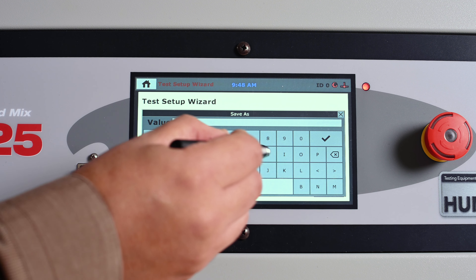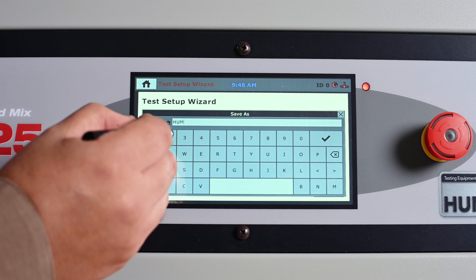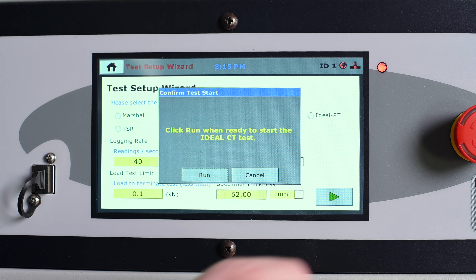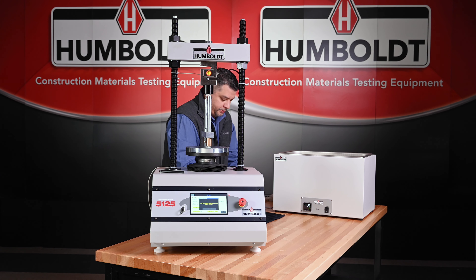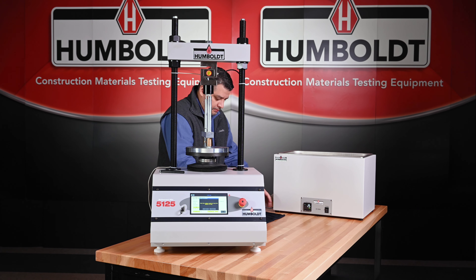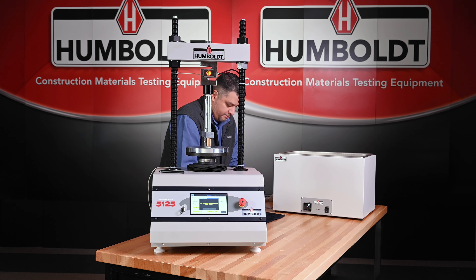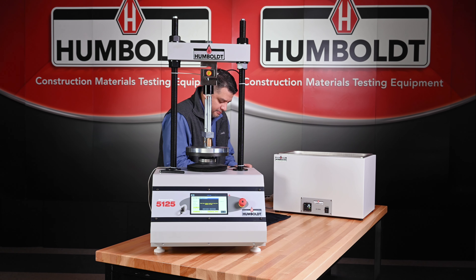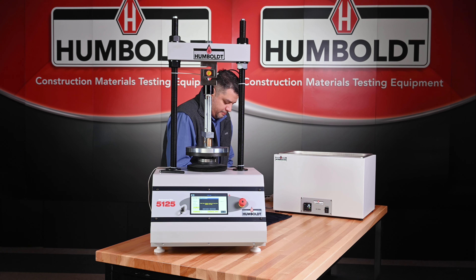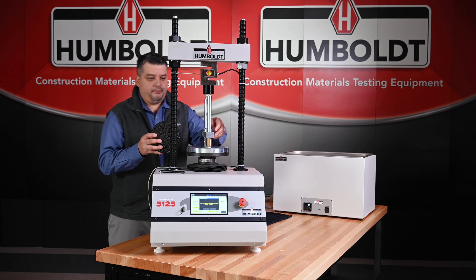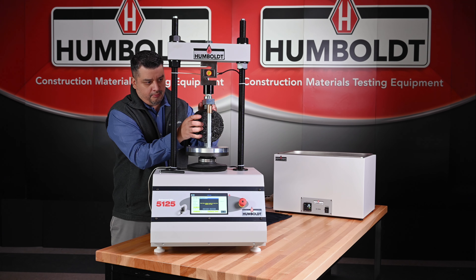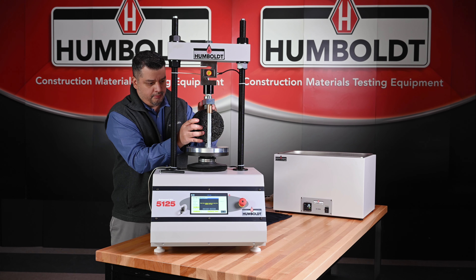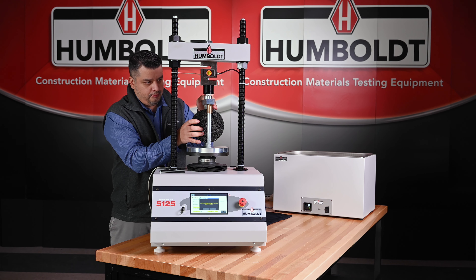On this screen, enter a desired name for the test and press the check mark to save the test name. At this point, you are ready to load the test sample into the frame. In this test, we used a 150 mm by 62 mm asphalt specimen, which was conditioned in a water bath at 25 degrees centigrade plus or minus 1 degree centigrade for 2 hours plus or minus 10 minutes. The asphalt specimen is removed from the water bath and patted dry, then loaded into the center of the test fixture in a vertical position.